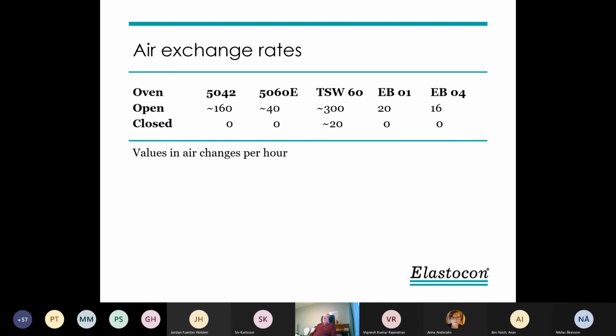Another thing is the air exchange rate. It's difficult to set on a normal lab oven, and it's even more difficult to measure. But sometimes they have a throttle you can set to 0 or open, and that can be a dramatic difference in the air exchange between closed and open. Of course, in an aging oven you need to know. So in our ovens we use a flow meter with a needle valve, so you can set the desired air exchange rate.